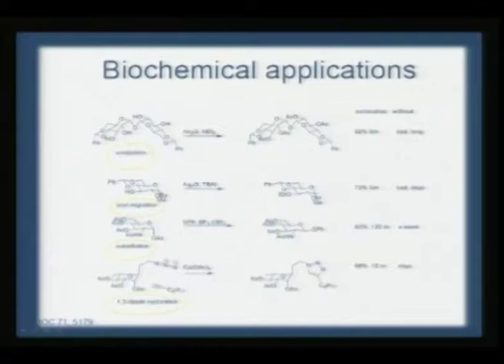As you carefully look at this reaction, you could see that most of it involves metals, metal salts as catalysts, and these metal salt based conversion reactions have a phenomenal effect when you try to use ultrasound. Without ultrasound the yield is very bad and it takes many days. This reaction is very slow, on the order of a week and several days, with almost very little conversion.